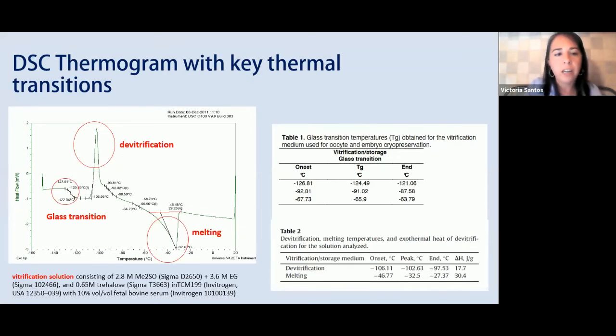Here we have the actual thermogram curve for our vitrification solution. You can see we have the glass transition at approximately -125°C, and the devitrification peak and the melting or fusion. And we could calculate the heat of devitrification and the latent heat of melting.